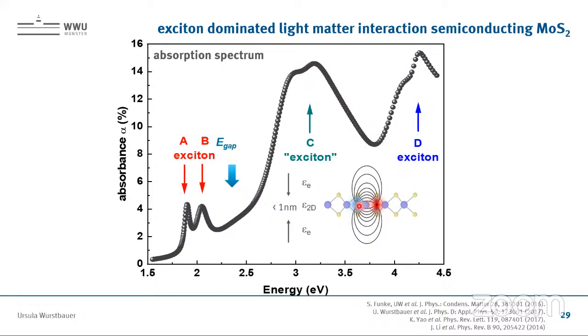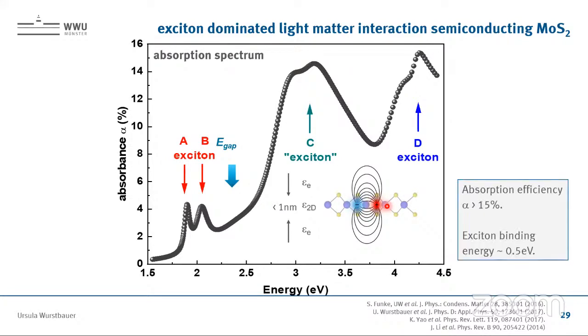An exciton, just to remind you, is an electron hole pair coupled by Coulomb interaction, and of course having some electric field which is screened by the environment. And what is quite peculiar here for these materials, and why we see the strong resonances, is that we have an exciton binding energy of almost half an eV, or up to half an electron volt, which is really huge. Just the binding of this electron hole pair. And maybe first of all, let me explain why we have this high binding energy